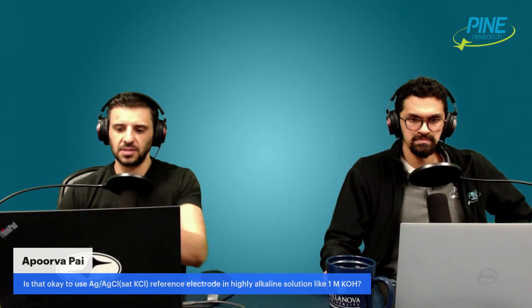And just for reference, Pine sells a single and double junction silver chloride reference electrode. I believe in our documentation, our recommendation is to not use it in greater than 0.1 molar KOH. As you said, the stronger the KOH, the faster things are probably going to go haywire. As a general rule, 0.1 molar KOH and lower is probably going to be okay for relatively extended periods of time, but 1 molar is certainly considered pretty strong, and you're going to start to see those problems. So just to give a number on it, that's what we recommend.